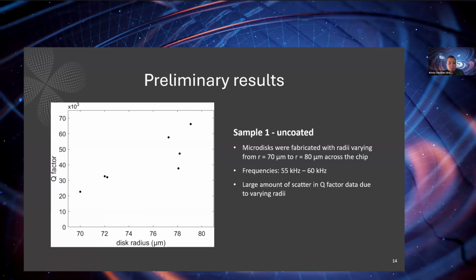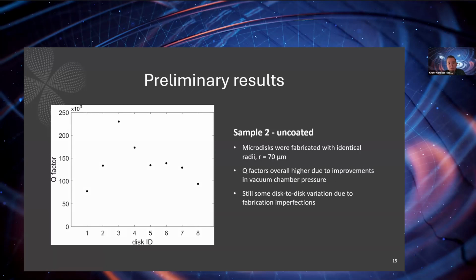The Q factors are of order 2 times 10^4 to 7 times 10^4, so plenty large enough to measure the loss of titanium dioxide. But there's a fair amount of scatter in the quality factor data because of the change in radii across the chip. We have a second sample, which we made in a later fabrication run, and here we chose to fabricate the disks all with the same radii so that, in theory, all the disks would be identical, with the hope that this would reduce the scatter in the quality factor data.